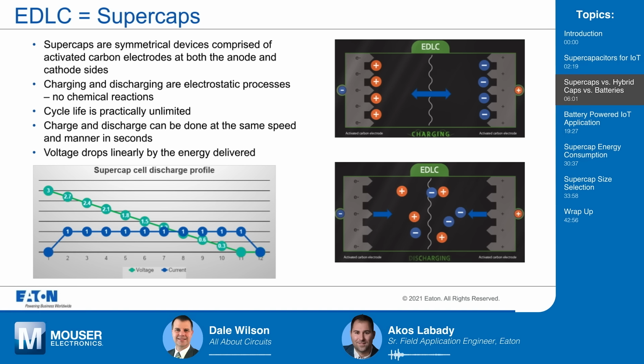The way it works is an electrostatic charge and discharge process. So it's very similar to the standard electrolytic capacitors or any kind of capacitors, but the only difference is that you have a huge terminal surface because it's a porous material, which is covered by the so-called Helmholtz layer. It's a special insulating layer coming from the type of electrolyte we are using. So that's why we talk about the molecular size of distance and the huge surface. This is why electrolytic double layer capacitors can store 5 to 10,000 times more energy than a standard aluminum electrolytic capacitor, for example. So it really works the same way.